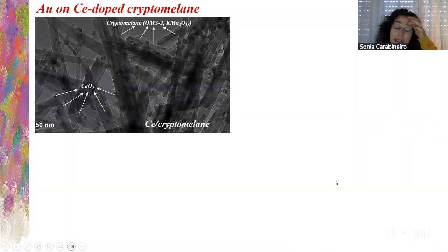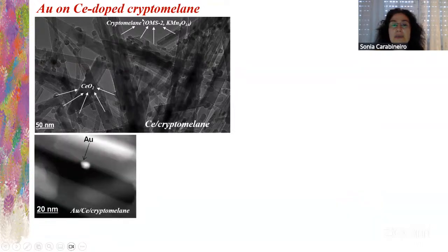For example, here gold on cerium-doped cryptomelane. So that's interesting. Cryptomelane is here, OMS-2, it's KMn8O16. It's an octahedral molecular sieve type of material. And see here, this might look like gold nanoparticles, but in fact, it's cerium oxide. If you want to see gold, only with this contrast technique.